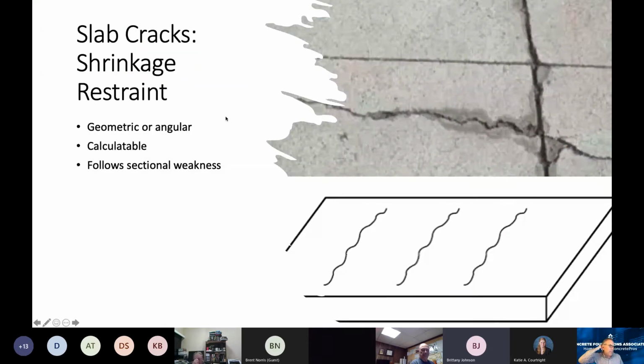Okay, so again, if I assess a shrinkage crack scenario, if you look at these two cracks, what this tells me based on the dimension of the joints is that the vertical joint adequately separated the two concrete sections so that we're getting movement. If we're getting shrinkage movement in the vertical direction, that's trying to compress the two slab sections on either side of that vertical joint, I should get relief from that horizontal slab joint. Because that slab joint's not thick enough, because it's a really tight line and it probably only went down maybe 3/4 of an inch, maybe an inch. And it should have gone down probably 1 3/4 inches.